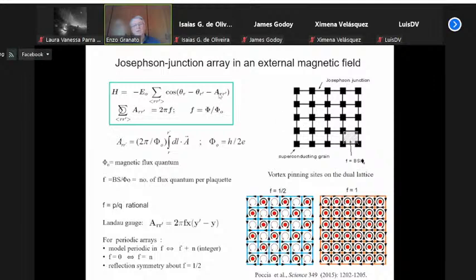And because the curl of the vector potential is related to the magnetic field, there is a constraint on these link variables: the sum of the link variables around the plaquette, which is the circulation of the vector potential around the plaquette, is equal to the flux penetrating that area, and therefore there is this constraint. You can write the flux in this form, which is dimensionless, where f is equal to the magnetic flux penetrating the plaquette divided by phi naught, which is the quantum of flux, h over 2e.